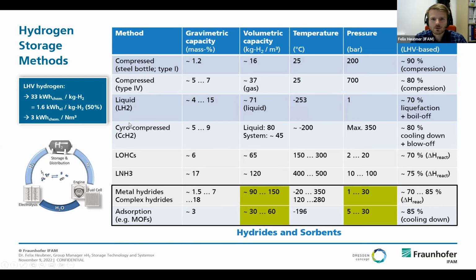And we can see, when we only have a look at the volumetric capacity of these materials, that they can store up to 150 gram hydrogen per liter. This is even more compared to 700 bar gas storage or even liquid hydrogen storage, because hydrogen is bound inside the crystal lattice, for example. And that's one of the very main advantages of this sorbent storage.